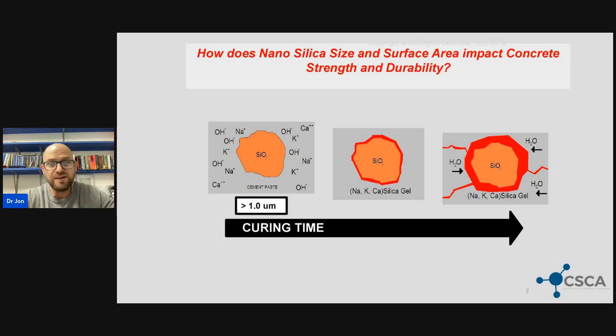So if you've never seen ASR, what we've got here is a reactive aggregate, and normally that aggregate has a tetrahedral form of silica that is susceptible to a breakdown because of change in pH at the interfacial zone between the hydrated cement paste and that reactive aggregate. Now, within that hydrated cement paste, there is a wide variety of salts within water, and we call that a pore water solution. It happens that the alkalis within that pore water solution, sodium, potassium, as well as calcium, break down the reactive silica and reorganize it from monomers to dimers and oligomers in a polymer into this hydrogel that has an expansive nature at that interfacial zone between the hydrated cement matrix and our aggregate interface.